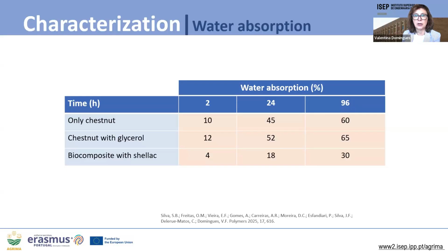Composites with glycerol show even higher absorption, surpassing 65% at 96 hours, attributed to glycerol's moisture-attracting properties. Shellac-treated composites demonstrated the lowest water absorption, approximately 30% at 96 hours, showcasing shellac's effective water resistance.